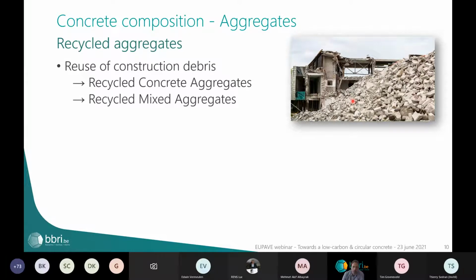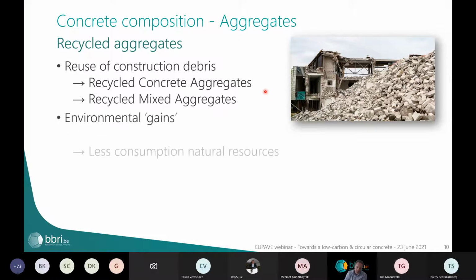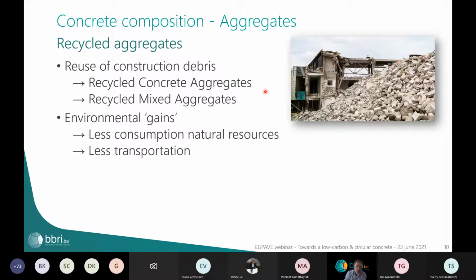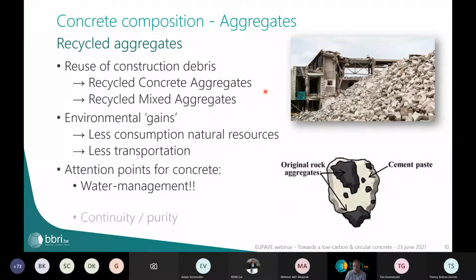That way, when we reuse them locally, we win in the quantity of aggregates that need to be quarried, and we also limit the quantity of debris that has to be put elsewhere. So out of this debris, we can get recycled concrete aggregates and recycled mixed aggregates. The gains there are, like I said, less consumption of natural resources and less transportation. Of course, we cannot put them into concrete as such without taking anything into account. We have to look at the water management, which is very important.